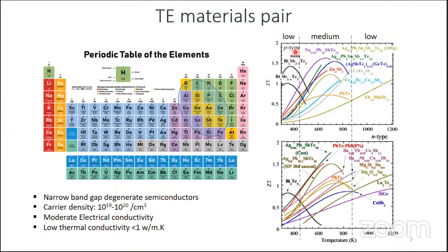But now commercial modules, if you see, most of the low temperature modules are made up of bismuth telluride. And these modules are mostly used only at 150 to 200 degrees Celsius, because beyond a certain temperature its properties start decreasing. So this cannot be used for very high temperature.